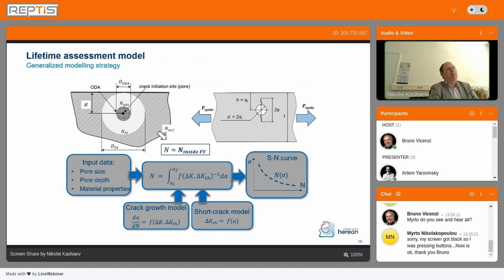But here we have some challenges. We are dealing with very small cracks for fracture mechanics. It means we need to know how the crack grows near the threshold behavior, and we need input data with regard to pore size, pore depth, and material properties.